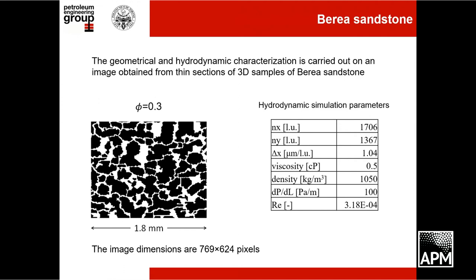This is an application of these methodologies to the image of Berea Sandstone. The porosity is directly calculated from the binary image. For the hydrodynamic simulation, we increased the number of cells with respect to the initial number of pixels to guarantee at least four lattices in the smallest pore throat. The fluid is water at reservoir conditions, and the Reynolds number is much lower than one, confirming we are in laminar flow and Darcy's law can be applied.